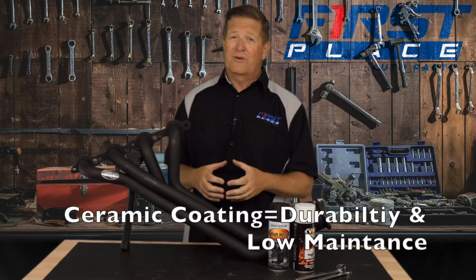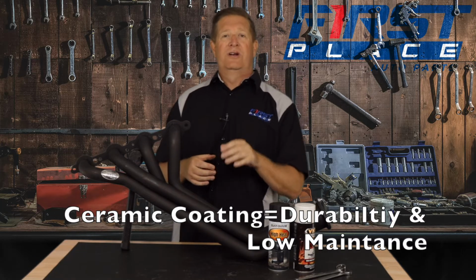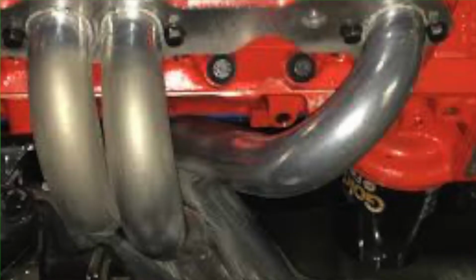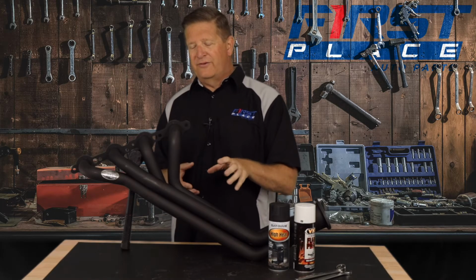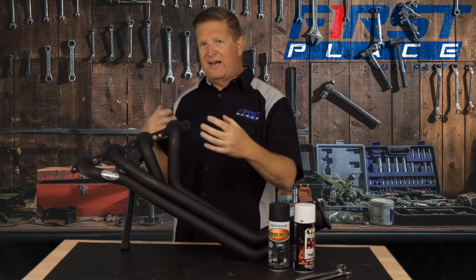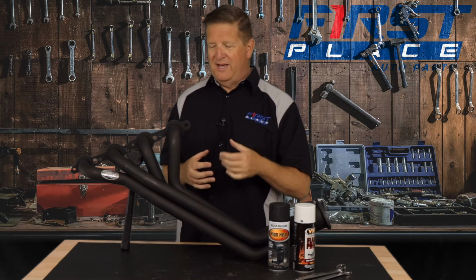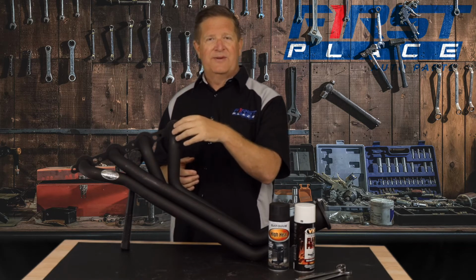The ceramic coated header, look, that thing's durable. It's going to look great for a long time unless you're going to break a camshaft in. Look, if you break a camshaft in with a ceramic coated header, what you're going to find is that coating is going to chalk up here. I've done this with the '56 Chevrolet. It had silver ceramic coated headers originally, and I broke a camshaft in and I had fans blowing on each side of the engine to keep the headers cool, but it didn't matter. After 5 or 7 minutes of above 2,500 RPMs, it did haze. It damaged the ceramic coating.